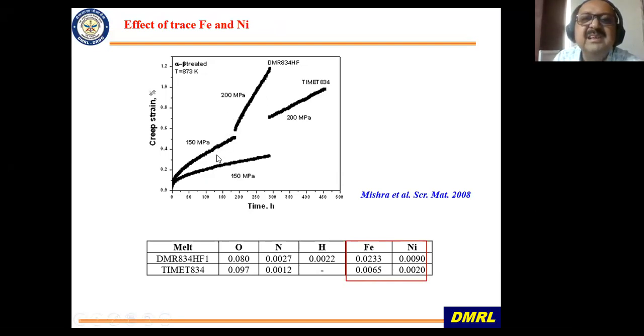Here you can see the two alloys. Timetal 834, which has much lower iron and nickel, as compared to DMRL 834, which has much higher iron and nickel. Mostly iron and nickel come from the titanium sponge and also the master alloys that you use, so you have to be careful with them. So you can see the jump in creep properties only because of this.